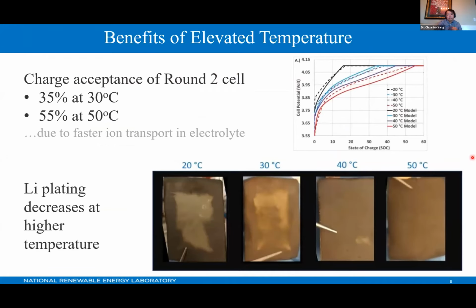To further investigate the extreme fast charging enhancement from temperature, a moderate loading cell was charged at 6C constant current CV for a total charging time of 10 minutes, at 20 to 50 degrees Celsius, and the results are shown as dashed lines in the top figure. After the 10 minute charge, the cell was discharged at C/2. Each cell was cycled only 5 times at one temperature, and then cut open in the discharged state to visually inspect for lithium plating.